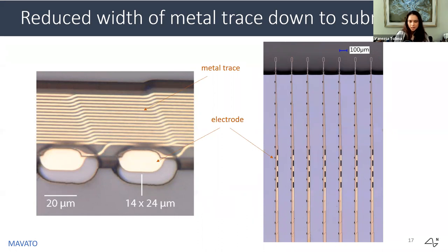We did this mainly in two ways. One was we reduced the width of each of the electrode wires, also called traces. In this manner, we were able to reliably go down to as small as about 400 nanometers per trace, which is thinner than some wavelengths of light. In the image, this is about 2 microns wide.